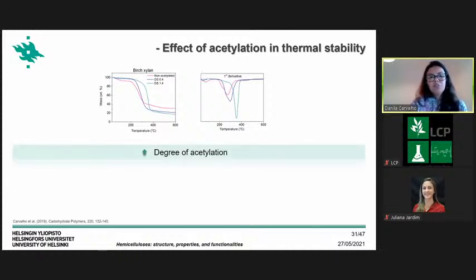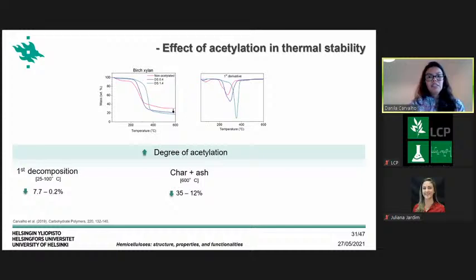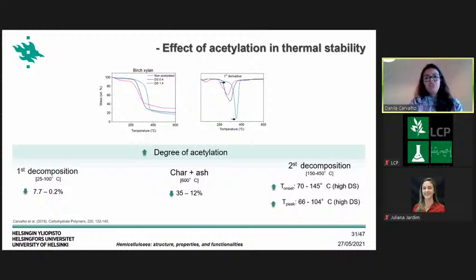Here, I just have the results for the birch, just to have some illustration, but all the different biomass sources present a similar result, which was that after the acetylation, the capacity to absorb water decreased, and the degradation by temperature was more efficient. But what really surprised us was the increase of the thermal stability, which means that the temperature at which the degradation of the xylan started increased from 70 to 145 degrees for all the biomasses, and also the temperature at which the maximum degradation of the hemicellulose occurred increased more than 66 degrees.